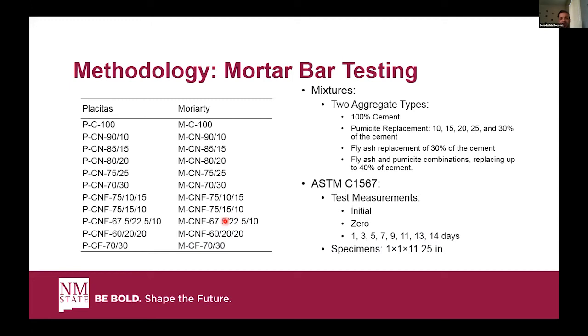Here, I'm going to talk about the materials and methods that we have used in this project. This project was divided into two main parts. The first main part was ASR test conducted on mortar bars based on ASTM C1567. 10 to 30% of the cement was replaced with the pumicite, 30% of the cement was replaced with the fly ash, and up to 40% of the cement was replaced with the combination of the fly ash and pumicite.